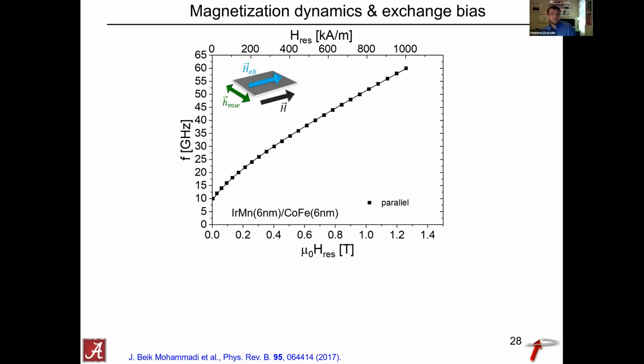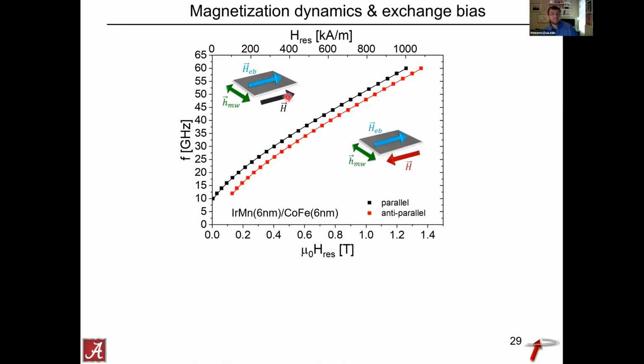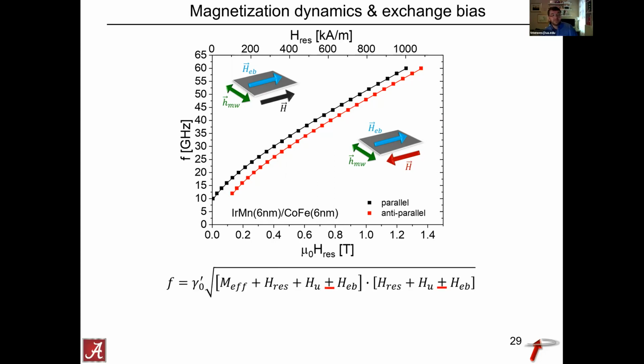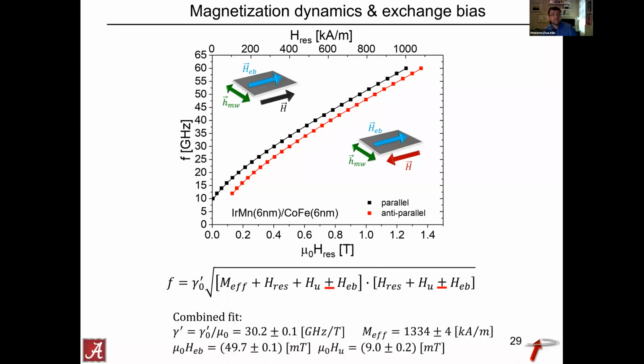First of all, you can do your FMR measurements, again, over a broad frequency range, and you can do it in two basic configurations, where in one case you apply the external field parallel to the bias field, and in the other case you apply it anti-parallel to the bias field. Because of that broken symmetry, these two resonance curves are shifted. From the separation of these two curves, you can extract the bias field. You can also try and extract uniaxial anisotropy that is very commonly observed in these systems. We can do that, and the curves that you see here fit the data with the parameters listed down there, which is good.